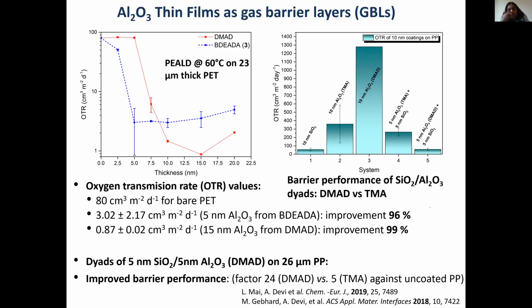Now the goal of the project was to see if we can test them for gas barriers. So here I can show you the oxygen transmission rate as a function of thickness. I grew the film of different thicknesses, 2, 5, or 20 nanometers, and then I measured the OTR. If you see the OTR in the beginning, basically it's very high, that means it's not good. The films of thickness less than 5 nanometers have a very poor OTR value. So the lower the value, the better it is. Now as you increase the thickness of the film, the OTR drops. That means around 5 nanometers, you are able to get good OTR values.